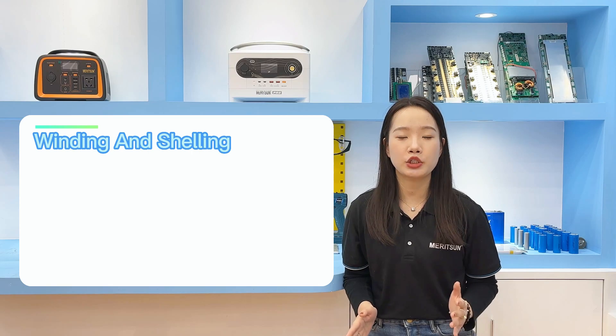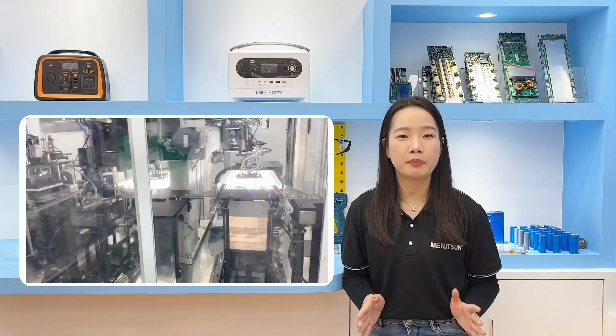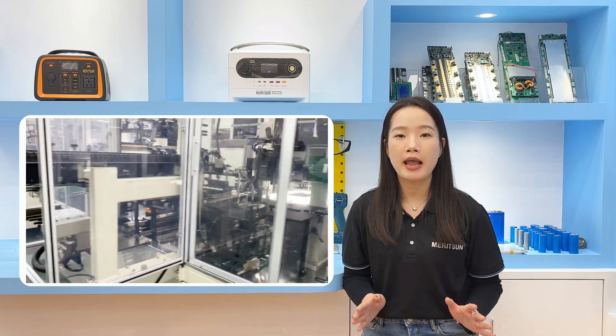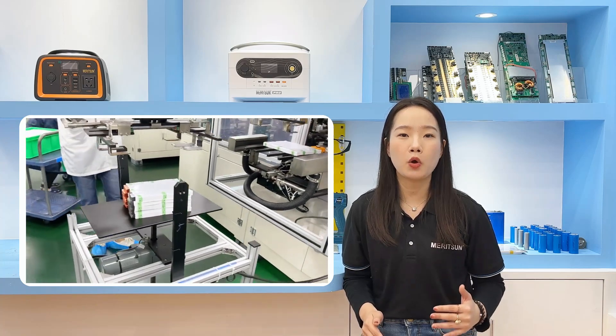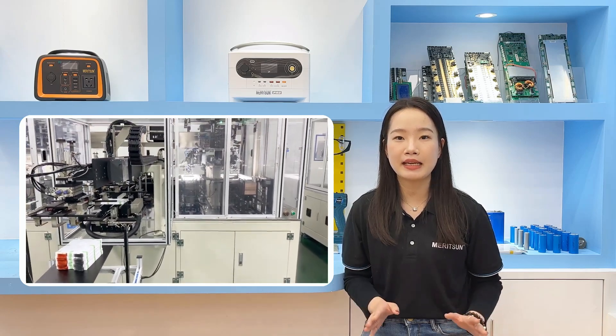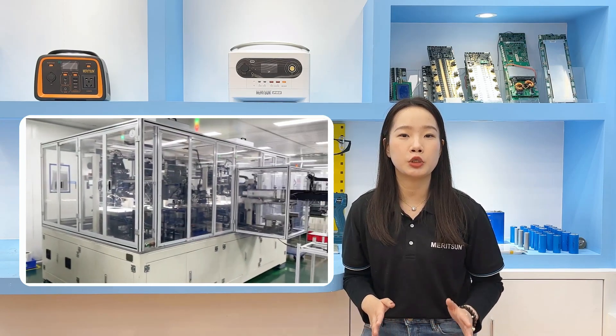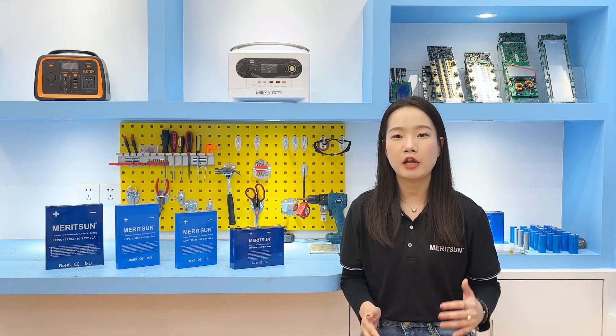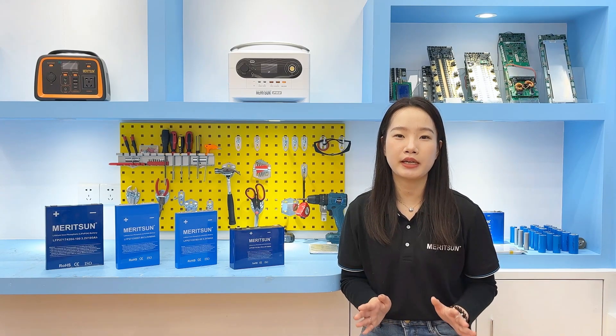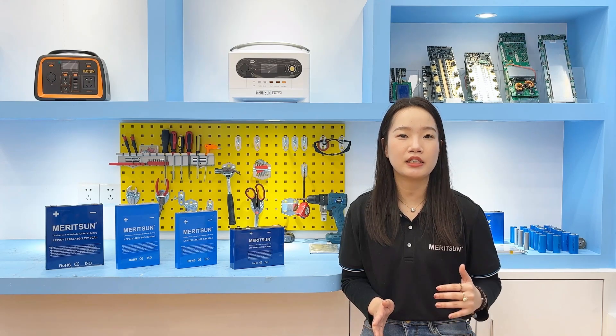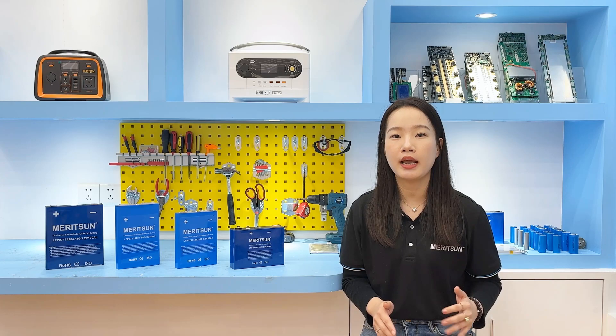The fourth process is winding and shelling: layering in the order of positive electrode sheet, separator, negative electrode sheet, and separator from top to bottom, and making the battery cell by winding. Depending on the type of cell, two basic cell assembly methods are generally used — stacking and winding — and the entire process is usually carried out on fully automatic equipment. After winding, the assembled cell structure is connected to the terminal by laser welding machine, and the subassembly is then inserted into the cell's metal housing for sealing, leaving an opening hole for the injection of electrolyte.